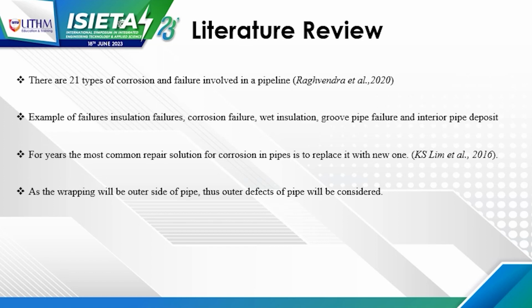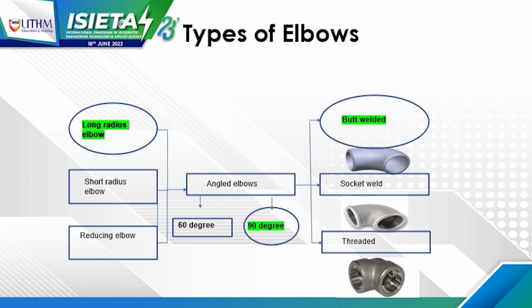For the literature review, there are almost 21 types of corrosion failure involved in a pipeline. Examples are insulation failures, corrosion failure, wet insulation, groove pipe failure, and interior pipe deposit. The most common repair solution is to replace it with a new one. By introducing this wrapping method of CFRP, we can retain the existing pipe by only wrapping the defected area of a pipeline, especially on the elbows. In this paper, we choose the type of elbow to be a long radius, 90-degree, butt welded elbow, due to its application in oil and gas pipeline transmission.